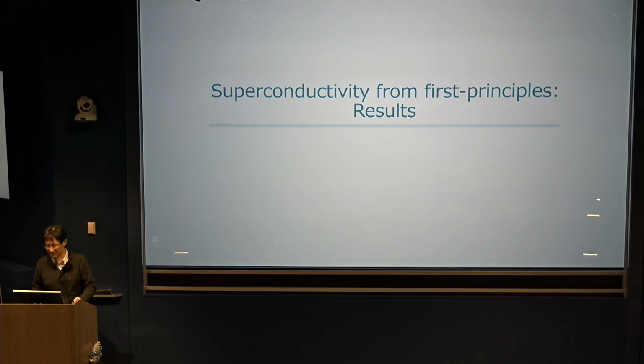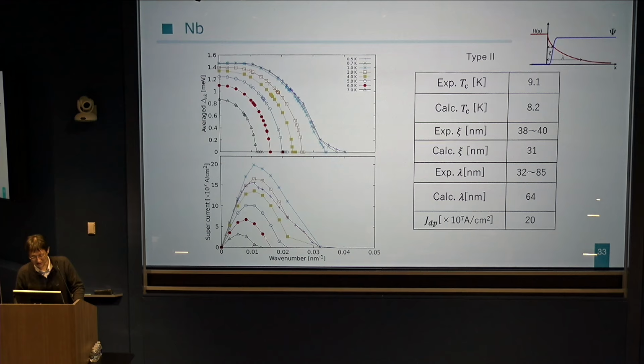So let us move on to the results. Okay, this is the result for niobium first. This is a plot of the gap function, or order parameter, as a function of wave number q for a variety of temperatures. At low temperatures, the psi is large, and at higher temperature, it becomes smaller and smaller. And this is a plot of current. It takes a maximum and then becomes smaller. This maximum value corresponds to the J_dp. And this is the result.